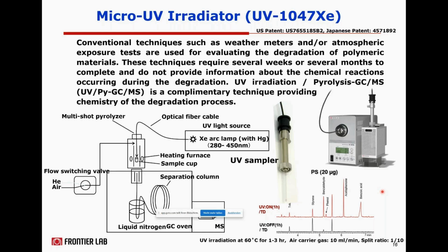The system consists of the xenon light source, the optical fiber cable, and the UV sampler. There are basically two analytical approaches possible. First is the online degradation study. That means analysis of volatile degradation products generated in the process of UV irradiation, in statu nascendi. Traces of degradation products are often generated during UV irradiation for several hours in air atmosphere. So it is possible to perform qualitative and quantitative analysis of those chemical species by TD-GCMS after online cryotrapping of these products at the tip of the separation column.